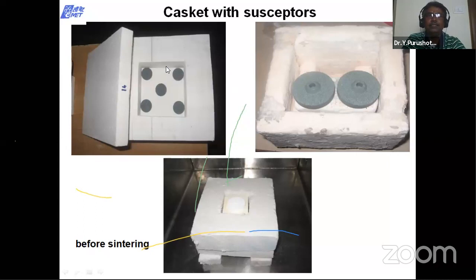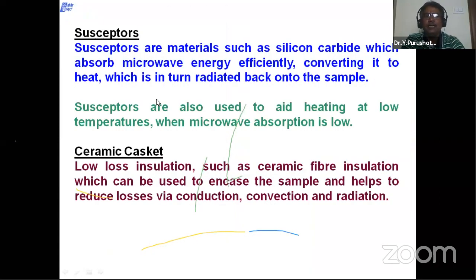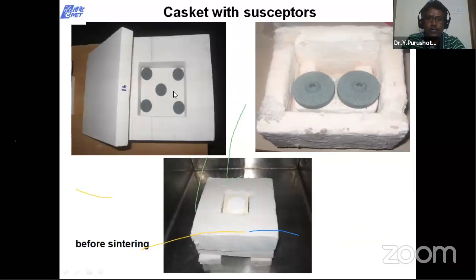And in the sample holder, suppose your material's microwave absorption is low, then at the bottom one can keep this susceptor. These are called susceptors. This is a silicon carbide susceptor, and silicon carbide is a very good microwave absorber. So if your sample is not taking heating, then if you keep this susceptor below, once you switch on the microwave, this will first absorb microwave and convert it to heat. Then that heat will be transferred here, and after that the sample will start heating. If your material is not microwave absorbing, otherwise this is not required.